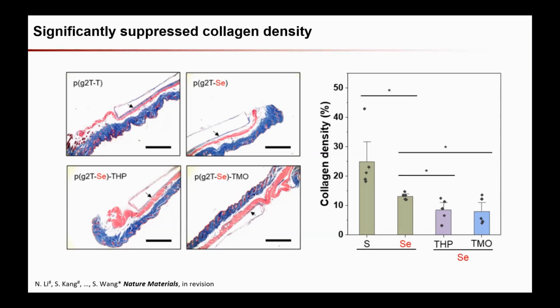To characterize foreign body response, what we are really comparing is where this arrow is pointing to. There's a blue structure that is showing the scar tissue. The result shows that if we utilize selenium to replace sulfur in the backbone, at only 1/3 of the ratio, it can already decrease overall collagen density by about 50%. And then if we further attach those immunomodulatory groups on the sidechain, it can further decrease the foreign body response by about 70% compared to the control polymer. So this shows these designs can work together in the way that we want.